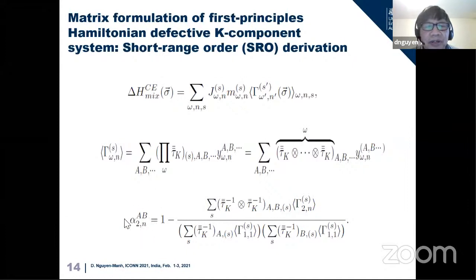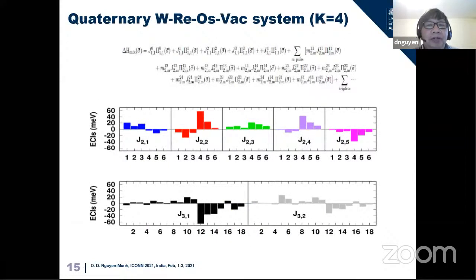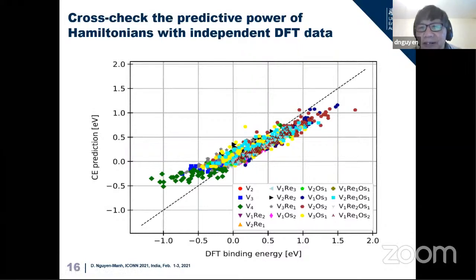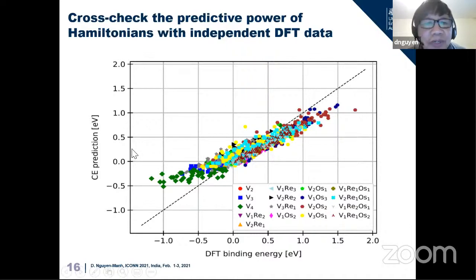The key point is that I am showing here the short range order parameters, which I will mention in the next few slides, and which can be presented in the matrix formulation. This is important for multi-component systems, for example an alloy with many elements, and also including the defect. So it is quite complicated, and we need a mathematical tool to compute it efficiently. For example, I take here the Hamiltonian for tungsten, rhenium, osmium with vacancy, which is already a 4-component system. We can build up the effective cluster interactions in the following Hamiltonian, and we independently check it against another independent DFT set to see whether the predictive power of our cluster expansion, built up from the previous slide, is good.